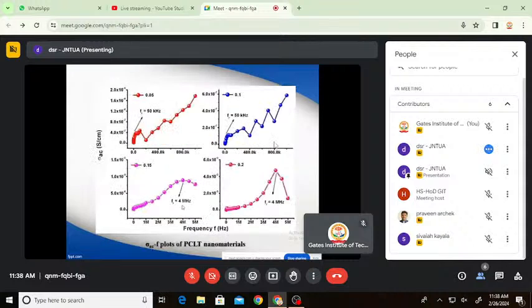Coming to AC conductivity, it is evident from the graph that the y equal to 0.05 and 0.1 compositions exhibited a systematic rising behavior up to 50 kilohertz. Above that, the two samples exhibited a small relaxation behavior, and after the relaxation frequency, it was observed as a flat trajectory. This may be due to the jumping frequency of charge carriers.